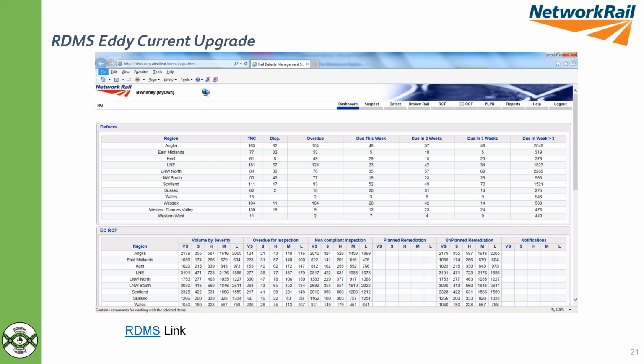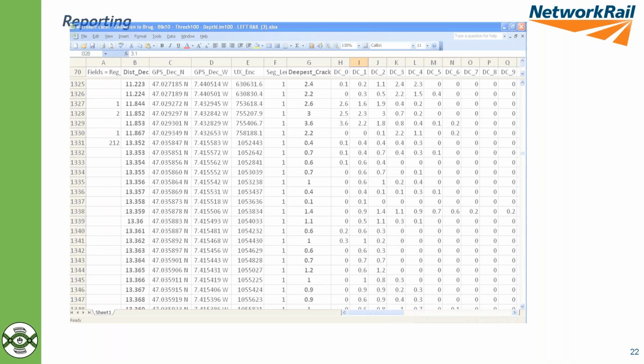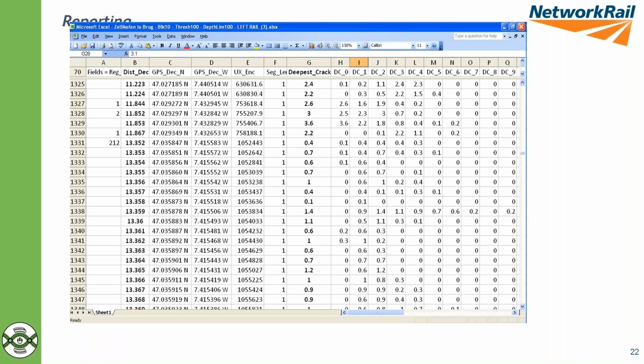So we made some changes to our rail defect management system, and we produce a lot of data from it. And an example here, this is a section of track. It's effectively every yard of track where there's RCF detected, and the system has the 10 probes, and that is measuring the depth of the RCF from the gauge corner to the field side of the rail. That's through the channels DC0 to DC9. They're always labelled that way round.